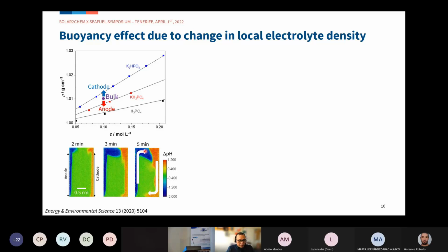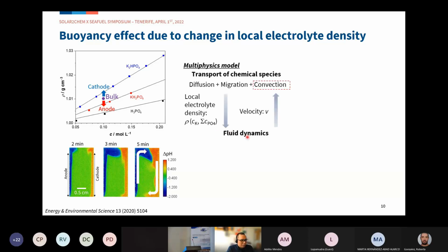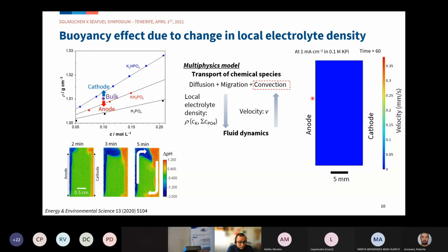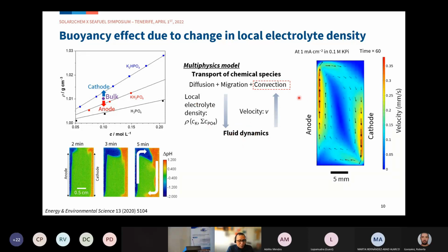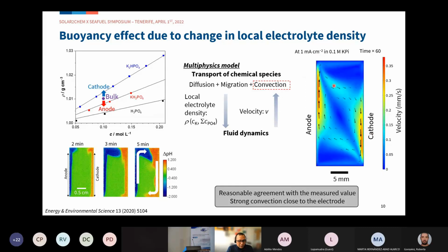To confirm this explanation, we updated our multiphysics model to include the effect of local electrolyte density to trigger the buoyancy effect in fluid dynamics. The result is shown here: this is the velocity profile as we perform electrochemical measurement or electrochemical water splitting. Indeed, the velocity profile of clockwise motion is also demonstrated here, and the simulated value is in reasonable agreement with the measured value.